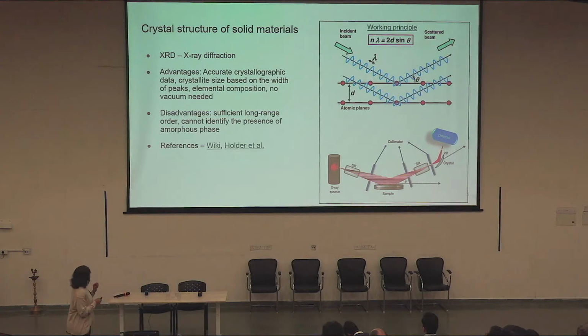Also, this technique is going to tell you what elements are present, not just the crystal information, but also the elemental composition. But the disadvantage is that you will only know information about whatever crystals are there in your sample, but you will not know anything about the amorphous phases, because an amorphous phase is not going to scatter the beam in a particular way for it to constructively interfere. So whenever you have a sample, you get some peaks. All you can say is that this particular crystallographic plane is in your sample, but you cannot say anything about the amorphous substrate.